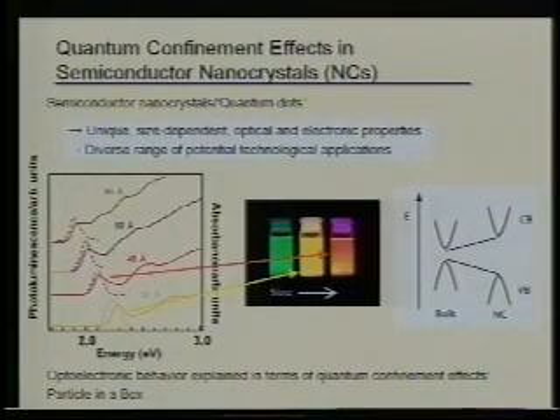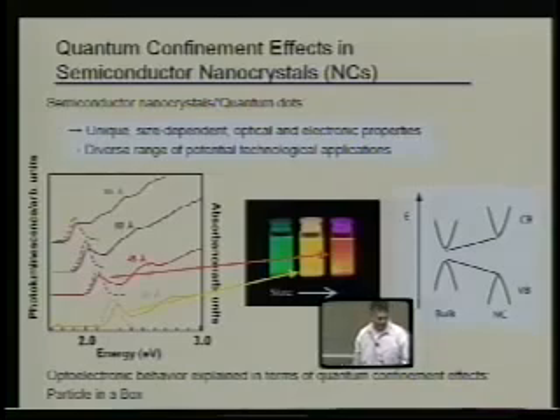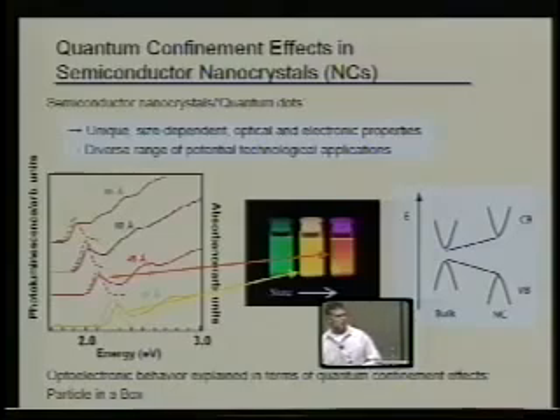All right, so another field that we do a lot in my group at Livermore is to look at the electronic structure of quantum dots. I'm quite sure you guys are probably more expert on these types of quantum dots than I am. So what I'm showing here is, again, cadmium selenide quantum dots. All the way over on the left-hand side, we show the optical absorption and the photoluminescence. As we know, as we change the size of our quantum dots, we can get them to emit different colors. So it has really nice applications for various